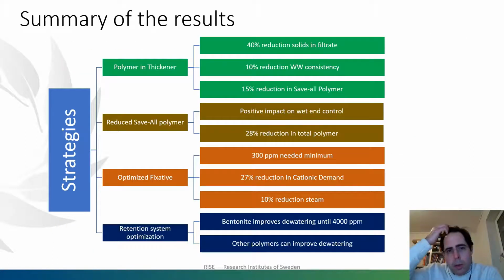Summarizing the results of the whole project, since I cannot go into detail on all of them: by adding the polymer in the thickener, we saw a 40% reduction in the filtrates. We managed to reduce even the consistency of the white waters of the paper machine, and a 15% reduction in the polymer to the save-all. In addition to that, working with this polymer, we managed up to a 28% reduction, with a positive impact on the wet end control. We optimized the dose of fixative to the bare minimum, and we saw this 10% reduction of steam with a 27% reduction in cationic demand.